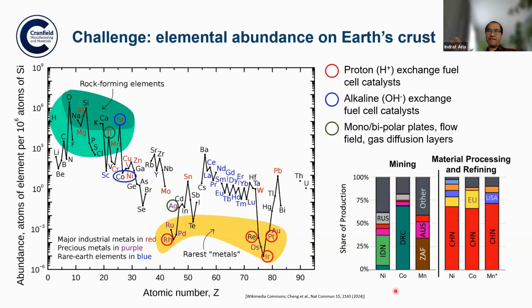The good thing about nickel, just to highlight, is that Indonesia is one of the biggest producers of nickel. So there's a big mining of nickel in Indonesia. However, you have to be careful here. Most of the nickel is currently processed and refined in China. So there is still a geopolitical issue. But if we can refine and process all the nickel domestically in Indonesia, then imagine you hold the share of catalyst production for the hydrogen economy, at least 35-40% of that. So I think that's a win.